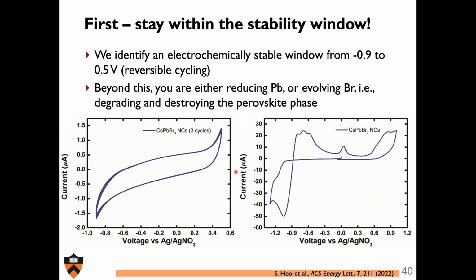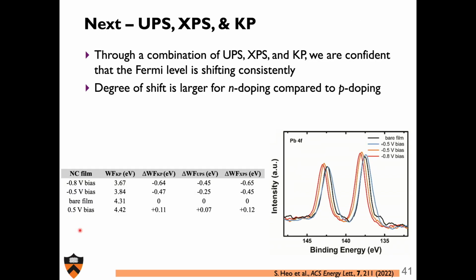We were very careful not to go beyond the electrochemical stable window. In the case of cesium-lead bromide, for us, that was about minus 0.9 volts to 0.5 volts. If you push beyond it, you see all kinds of electrochemistry unfolding, and you are reducing lead. You see lead zero in the system. You are evolving bromine. So that's not a good idea. But if you stay within the stability window, you can see a nicely reversible cycling. And you can get real change here.